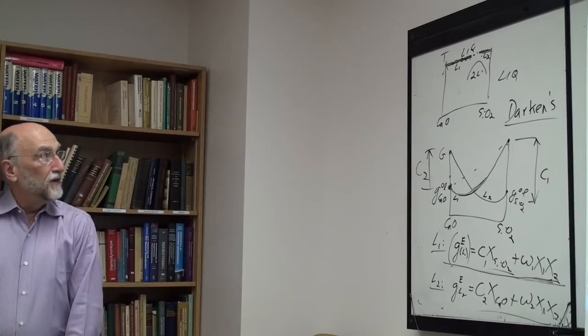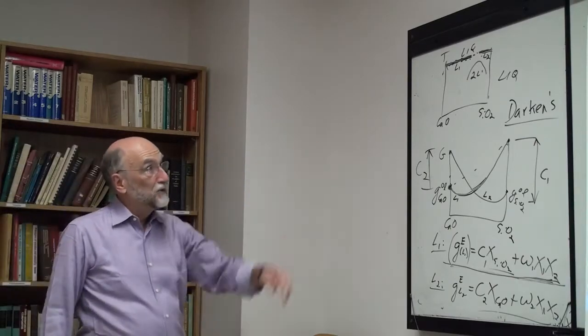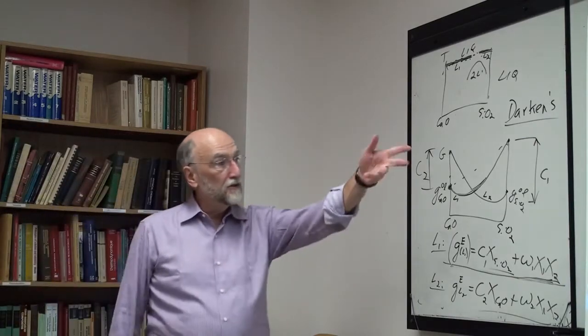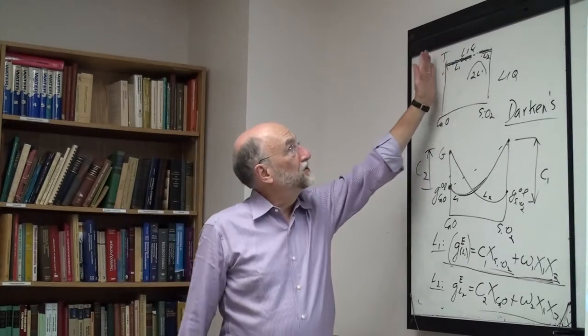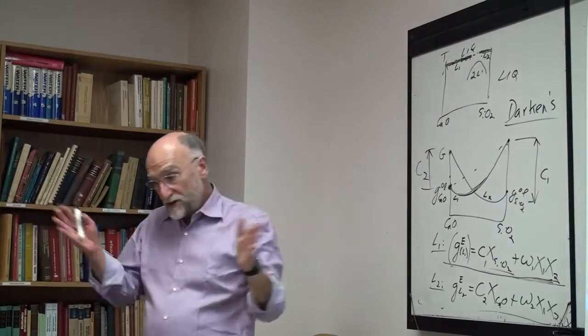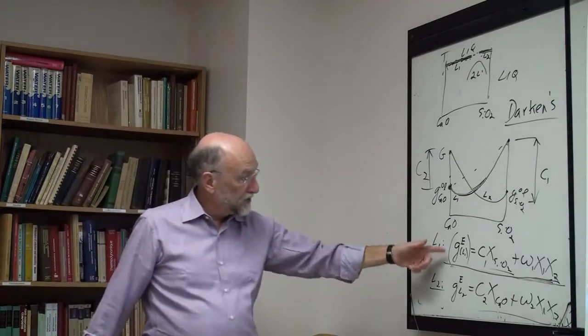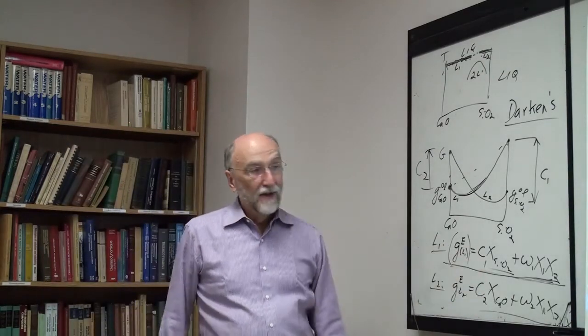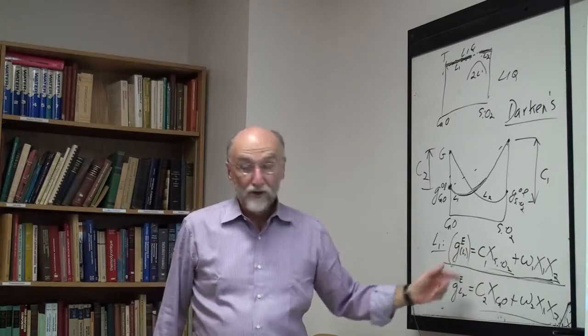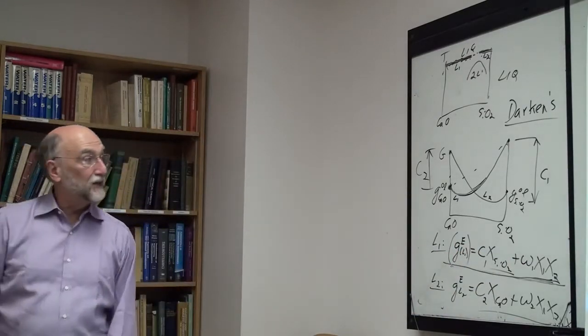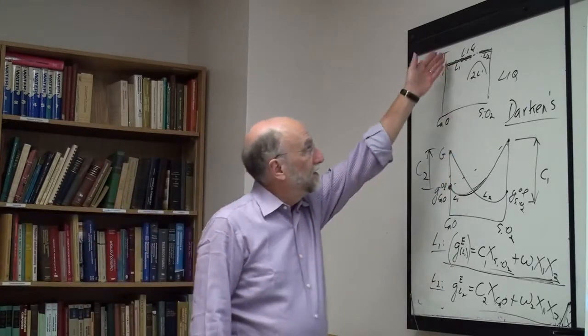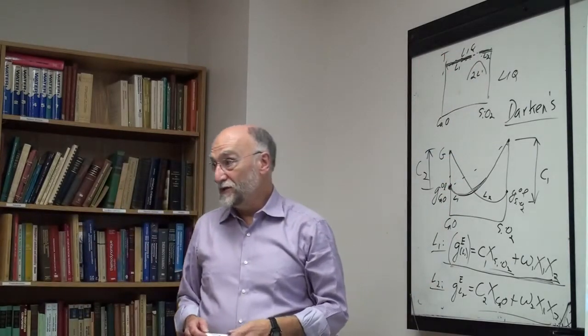But he showed there are an awful lot of systems, mainly liquids, that obey this kind of thing that I showed you the other day, silver chloride, silver sulfide. There's a very narrow transition region, and to express each terminal region with these two equations, you can get a very simple fit with just two parameters on either end, a beautiful fit, indicating there really is something physically correct about the model. Unfortunately, it doesn't apply over the entire composition.